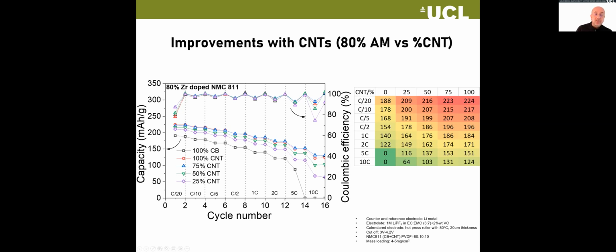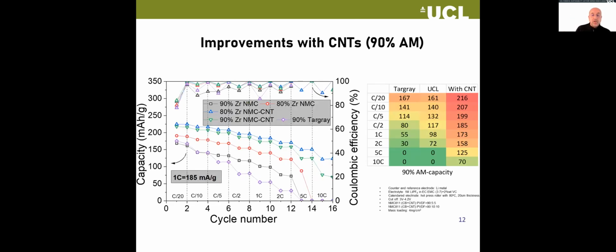Most battery companies are interested in much higher than that. They want 90 or 95% active material, but it means you're generally adding less conductive. So we also looked at the possibility of adding 90% active material. And here's the data for that. And this is just a selection of data.